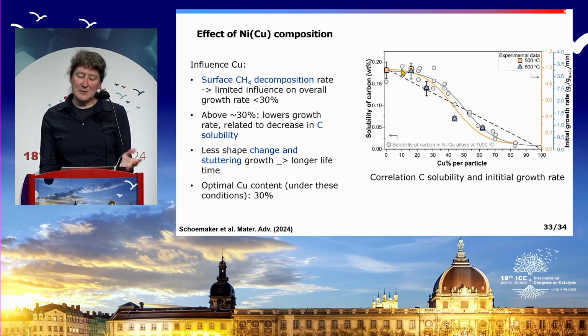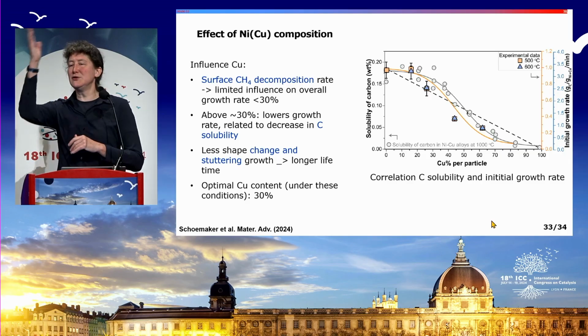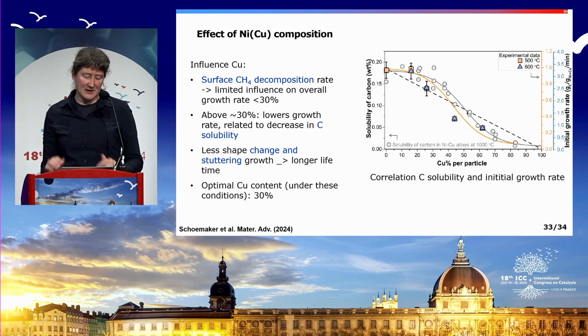So what we think is that a bit of copper helps, because you have a better solubility, you have less deactivation, but at some point your solubility becomes so low that, again, you decompose methane and it forms carbon there, and then it stops growing.